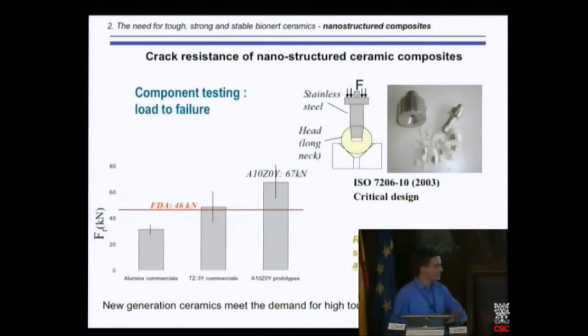So what about this new alumina zirconia nanocomposites prototypes versus current alumina and current TZP ceramics? So here is the load to failure of commercial alumina. So 7 tests were done for each material. So this is the standard deviation. Zirconia, 3YTZP. So reminder, modest crack resistance, stable. Here, high crack resistance but not stable. And here, what you find is highly resistance and highly stable.